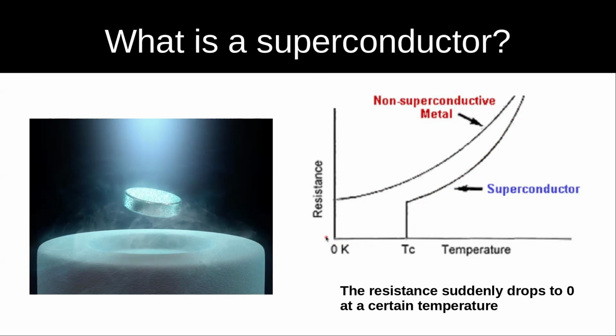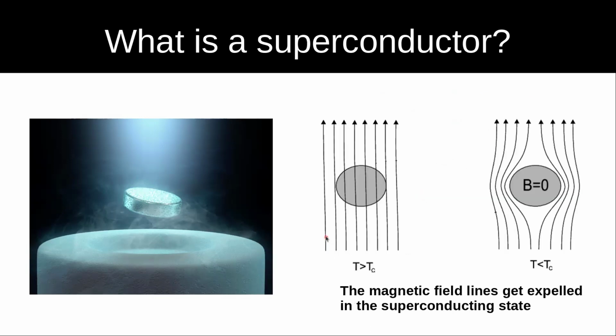The temperature at which this drop happens is what is called the critical temperature of the superconductor, and it's the temperature at which we have gauge symmetry breaking. One of the important properties of superconductors is something called the Meissner effect. The idea is that if you have a metal in a magnetic field, in principle, a metal is compatible with a magnetic field, so nothing happens if you are above the critical temperature. But once you go below the critical temperature, the superconductor completely expels the magnetic field, and the only magnetic field remaining inside the superconductor must be in quantized vortices, at least in type 2 superconductors. This is another signature of the superconducting state, and this is directly a consequence of gauge symmetry breaking.